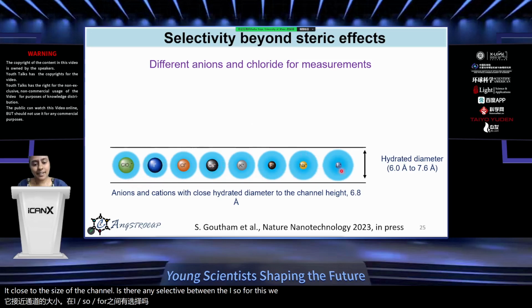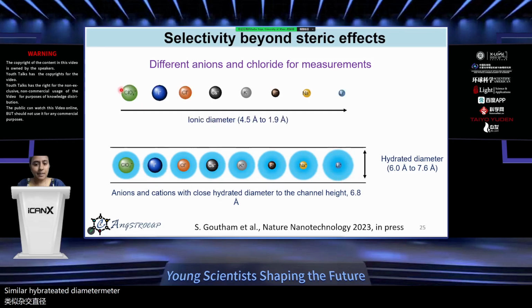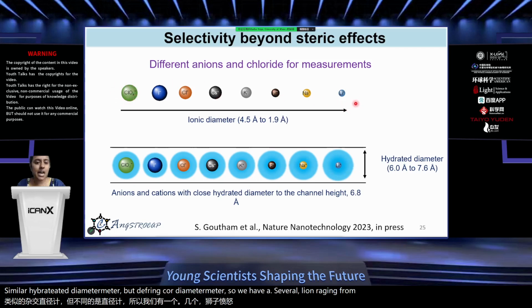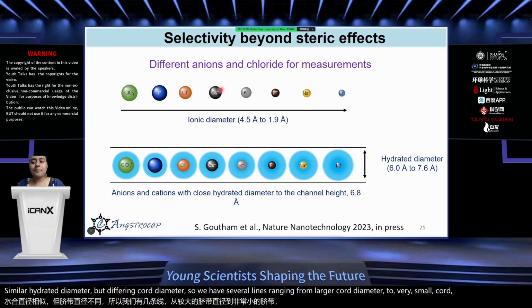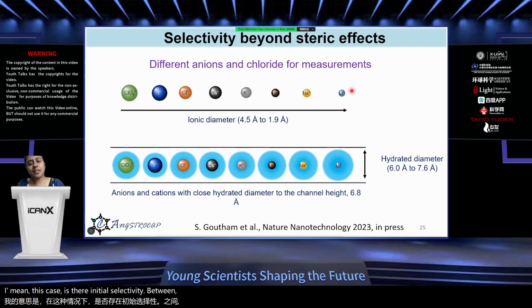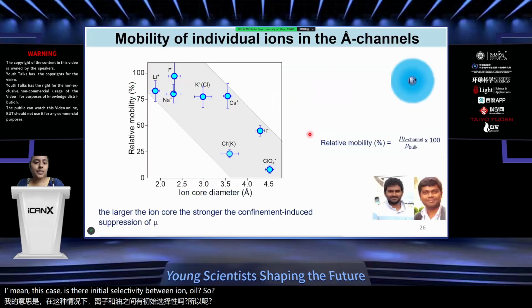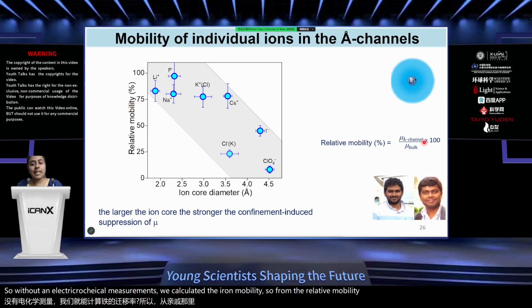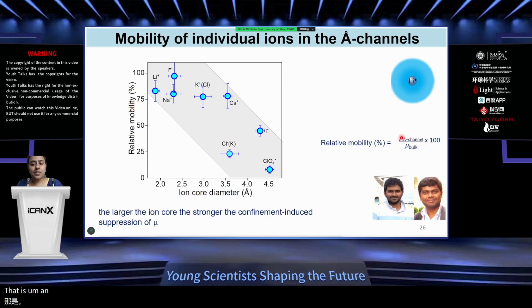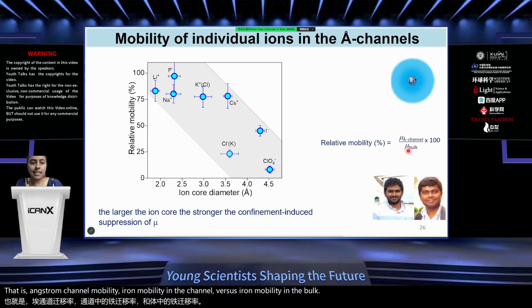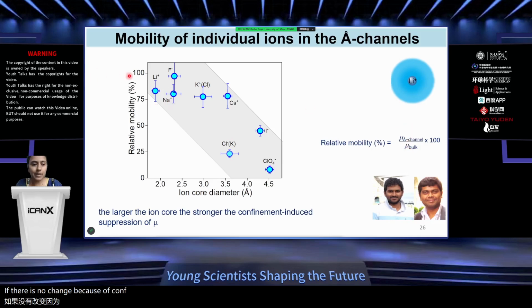So for this, we selected several ions which have similar hydrated diameter but differing core diameter. So we have several ions ranging from larger core diameter to very small core. And in this case, is there any selectivity between ion to ion? So with our electrochemical measurements, we calculated the ion mobility. From the relative mobility, that is the ion mobility in the Angstrom channel versus ion mobility in the bulk, if there is no change because of confinement, it will be 100%.